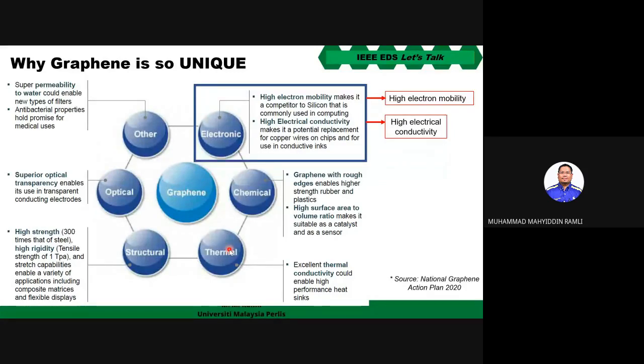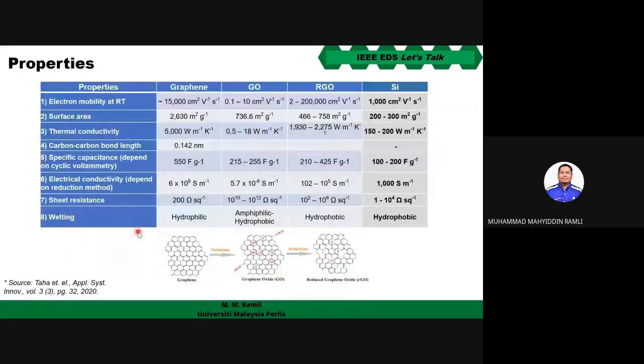And then the structural and the optical properties. So if you look at here, we get all the values here. If you compare the graphene and then the graphene oxide by using the chemical exfoliation, and then we further reduce the graphene oxide, and then we compare with the silicon value. For example, here we have the electron mobility. So if you look at here, this electron mobility, if you compare with the silicon, of course, it will beat the silicon and become a really good and ideal candidate in terms of the electron mobility.